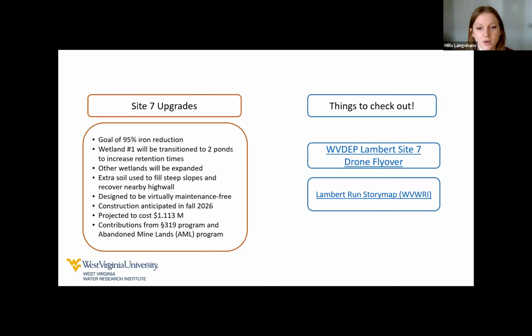But moving forward, I called it Site 7 upgrades here. It's really more of a remodel, just because of how much we are doing to it. The goal is to be at a 95% iron reduction, so we want to move up from that 70% to 95. In order to do this, we have decided to change a couple things. So that first wetland will be changed to 2 ponds, so that the water has more time to slow down and spread out, and so some of those particulate metals can settle out and get out of the free-flowing water. In addition to this, other wetlands will be expanded, so we have, again, more retention time, more time for those particulates to get out of the water.